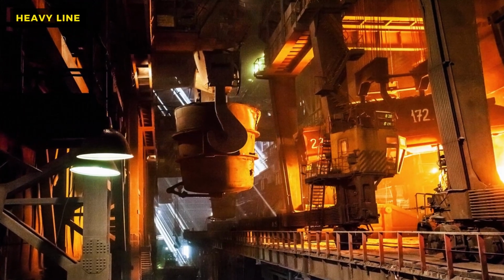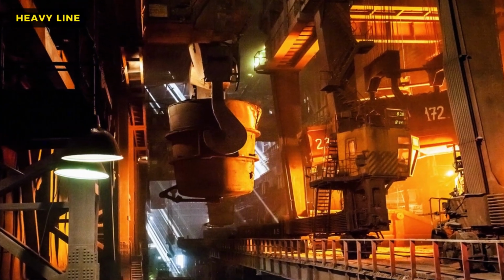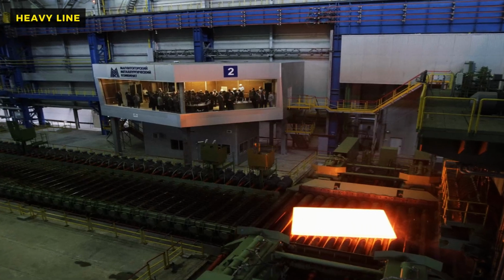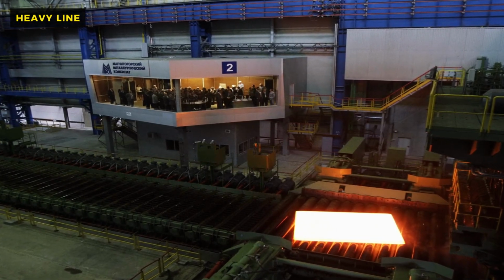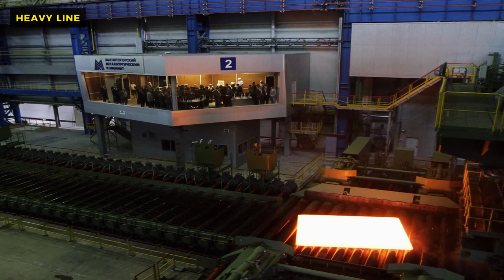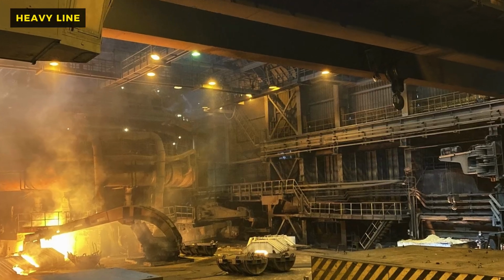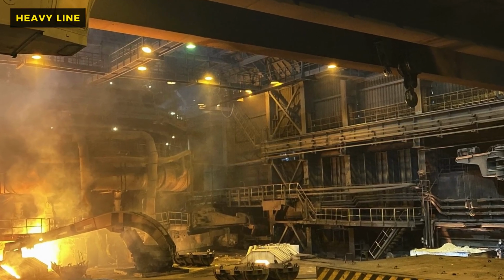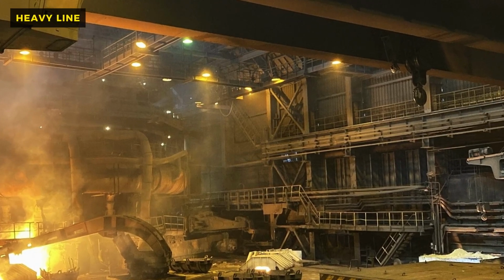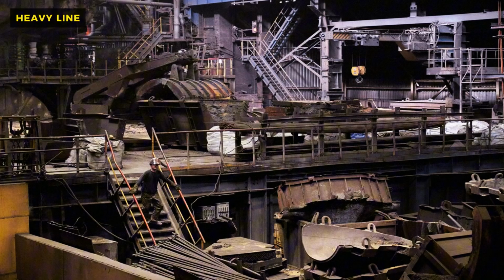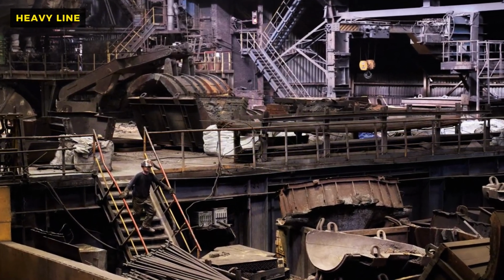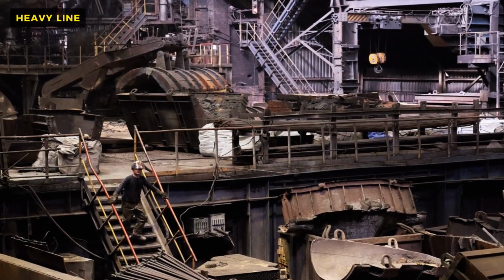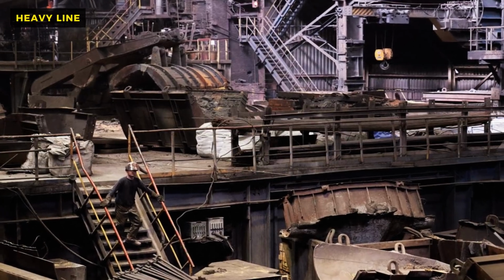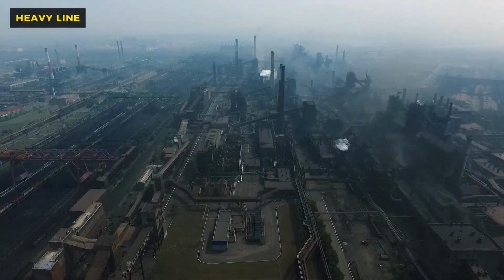Impurities like silicon, manganese, and phosphorus are oxidized and trapped in a layer of lime flux floating on top. It is a ferocious process, lasting only about 20 minutes. Think of it like blowing bubbles into a glass of milk with a straw, except the milk is liquid steel, the breath is supersonic oxygen, and the bubbles are burning carbon monoxide. The vessel vibrates, the building shakes, and a roar fills the hall that renders speech impossible.